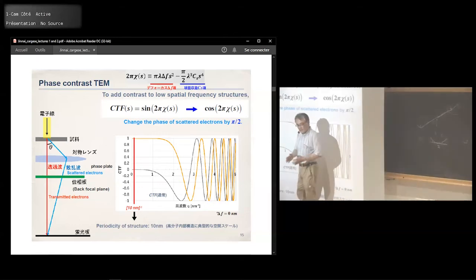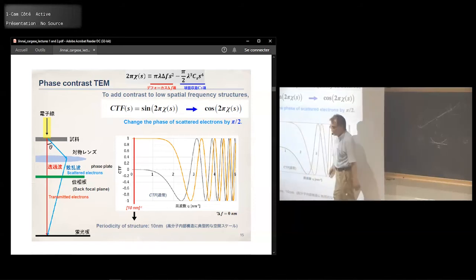The structure of a polymer is typically on the order of 10 nanometers, for example 20 nanometers. The scattering angle corresponding to this is somewhere here. So up to here, it's almost 0. So there's no way for the large structures to be imaged with this phase contrast.